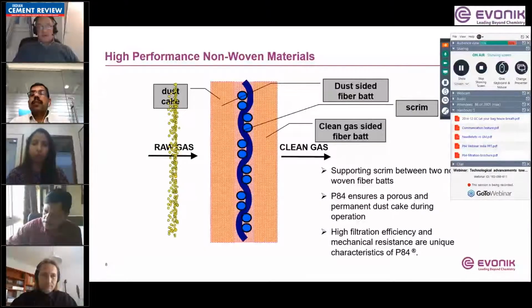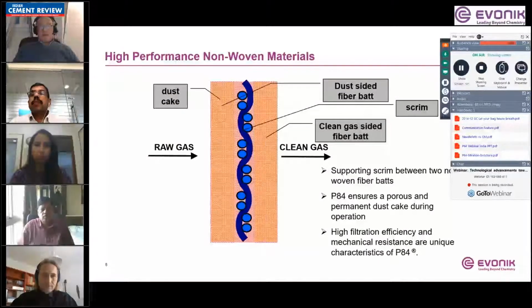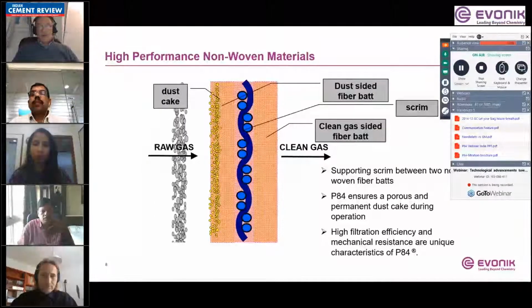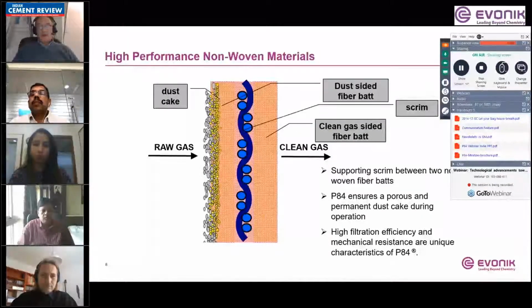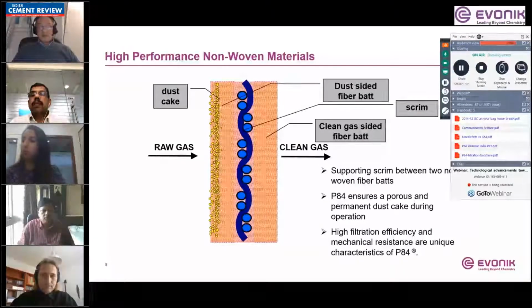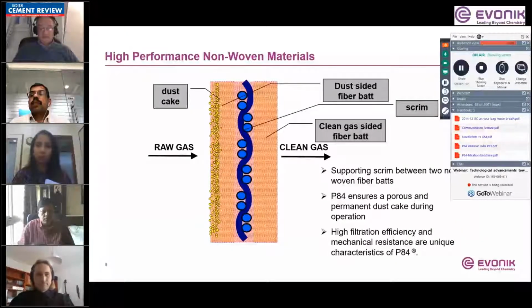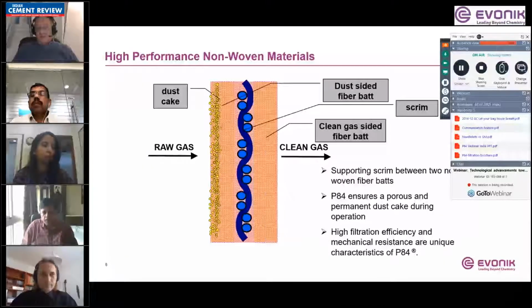I would like to show what happens during the initial phases of a P84 bag pre-coating. You see that a certain amount of dust accumulates on the fibers, and only after the process dust is arriving, we can allow jet cleaning, which removes the process dust but does leave the pre-coating dust there, effectively protecting the filter media. High-efficiency filtration, in fact, is a unique characteristic of P84, together with its mechanical resistance compared to the PTFE membrane mentioned before.